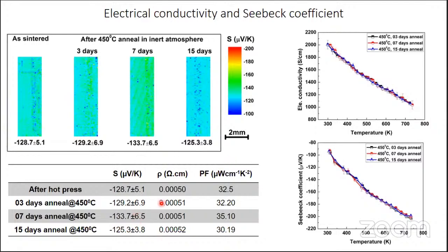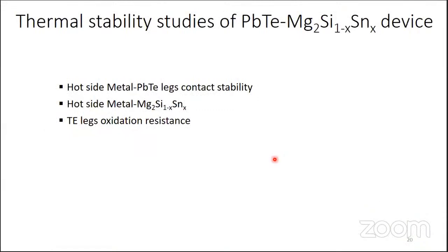And see, this is the result of 15 continuous days at 450 degrees Celsius of annealing, and then we measured the Seebeck coefficient and resistivity. It shows very consistent values, it is not degrading or undergoing any thermochemical changes. The power factor is also comparable. So this also shows very good thermal stability. Unlike this LAST, it is not showing any degradation, pore formation, sublimation or oxidation in normal condition up to 450 degrees Celsius.